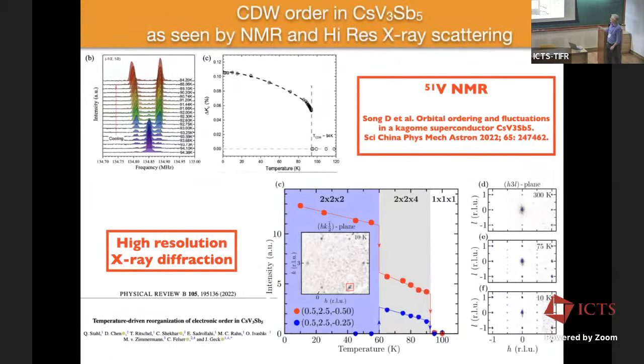Yeah, so just looking at that in a little bit more detail, this shows two sets of order parameters, one from the Knight shift for vanadium NMR, which really is a high resolution type measurement. So here's the data here. And you see not a lot of structure, but a very abrupt drop at exactly 94 Kelvin, and then no Knight shift beyond that. And then here's one of about 5 or 6 published high-resolution X-ray diffraction studies, which actually show a somewhat different order parameter. There's two different.